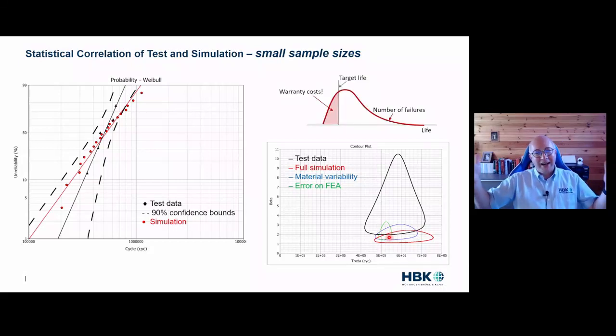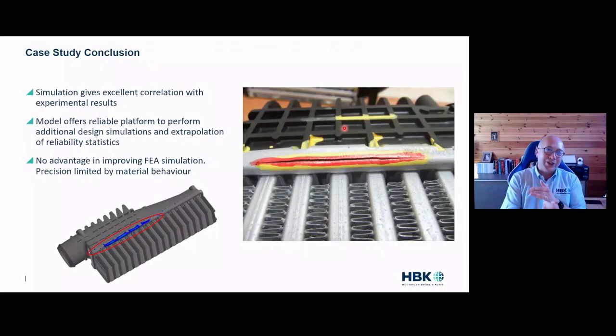And of course, by combining the tests and the simulation, we're much more able, with high confidence, to say, I'm happy with this target, I'm happy with my reliability estimate, and my simulation is actually starting to be verified by my test. So what has this shown us? First, that simulation gives excellent correlation with experimental results in this case. The model offers a reliable platform so we can perform additional design simulations if we want to, and can extrapolate and create reliability statistics. It's also shown us there would be no economic advantage in improving the FEA simulation. The precision in this case is limited by the material behaviour, not our finite element simulation.